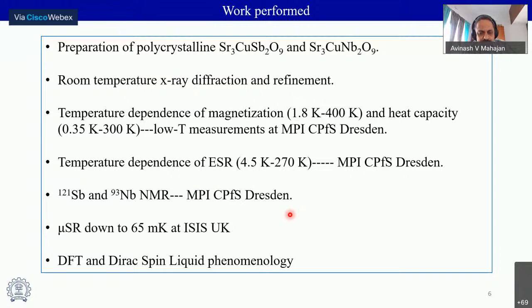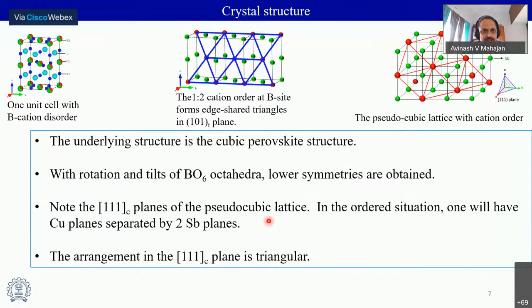And theoretical support from Indra and Sumiran, where there's an ab initio calculation of various exchange parameters, and explanation of this based on a Dirac spin liquid phenomenology by Sumiran. So to start with, the underlying structure for this system is really the ABX3 cubic perovskite structure. However, just on the face of it, the cubic perovskite structure is not geometrically frustrated. It does not apparently have any triangular sort of motifs.